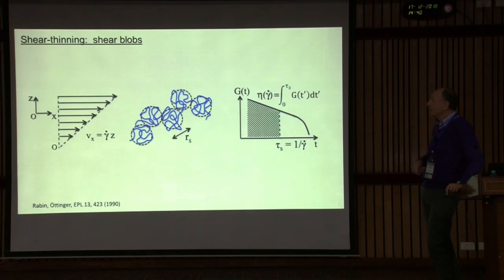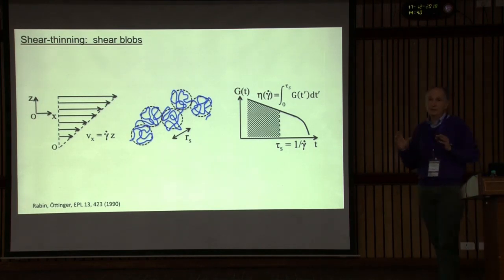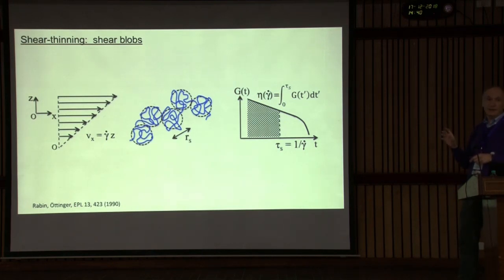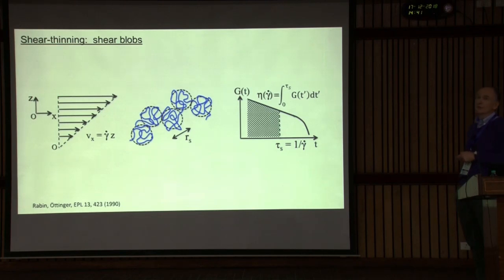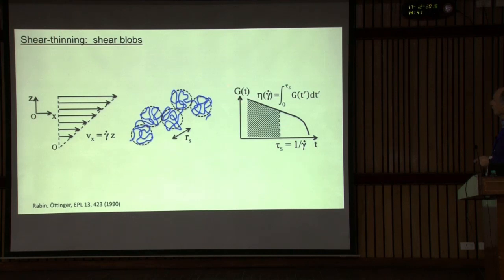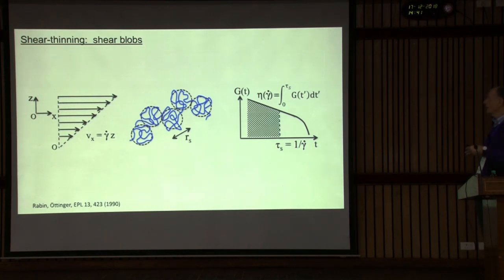This shear rate sets a divide between times which are shorter — within the blob there will be dissipation of energy — and times which are longer, where sections larger than the blob will deform with basically no dissipation. So the viscosity will come from the integral of G(t) up to the time which sets the characteristic time of the blob. This can be linked to the Cox-Merz rule, since sections larger than the blob will not communicate elastically between each other.